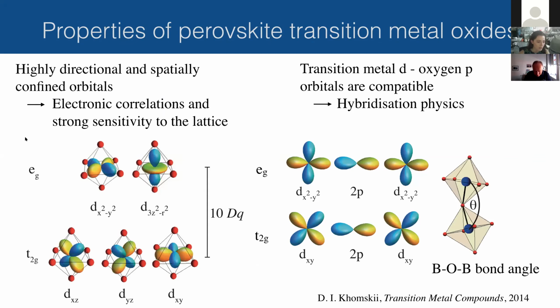But of course, when you put that ion inside a crystal, in this case just thinking about the oxygen octahedron, the orbitals have to somehow break their symmetry. And this is explaining how the symmetry of the transition metal d orbitals is broken inside the perovskite cage of oxygen. So what you get is a splitting between the orbitals which are pointing towards oxygens and the orbitals which are pointing away from the oxygens. You can understand why the t2g manifold, as it's called, is at lower energy, because the electronic orbitals are negative and the oxygen anion is negative. So this is a lower energy configuration than this one. And this splitting between them in energy is denoted 10Dq, which is also called the crystal field splitting. It's really coming because of this difference in symmetry.